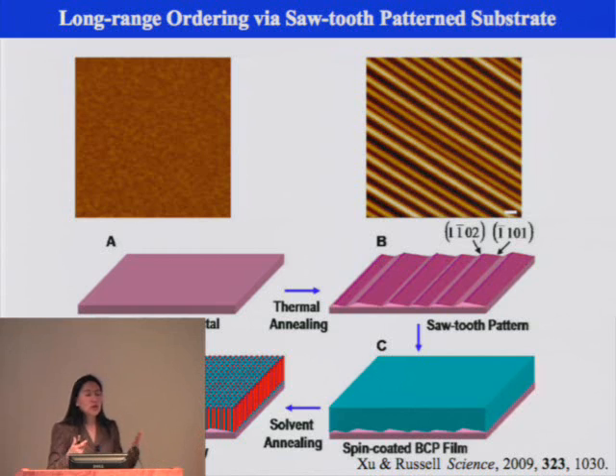So if we can translate the atomically ordered single crystal of the inorganic material and use it to guide the assembly of the block copolymer, then we should be able to get this microscopic aligned microdomain with long-range order. But the question is: inorganic materials are atomically registered, while polymer microdomains are typically 10 to 100 nanometers - you have like 1 or 2 orders of magnitude difference between those two. How can you translate this atomically ordered single crystal into a few nanometer or tens of nanometer ordered block copolymer microdomain?